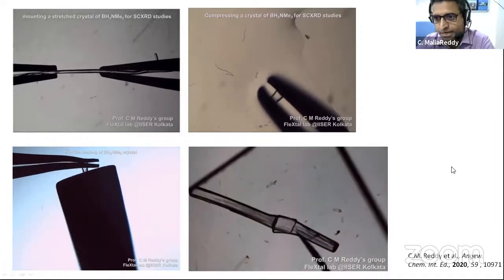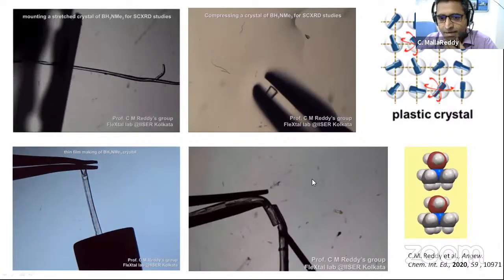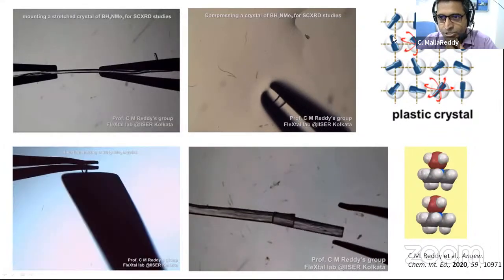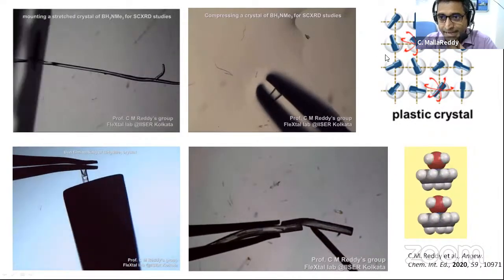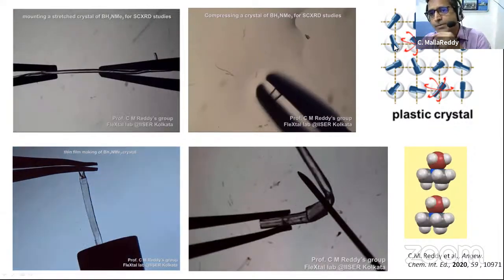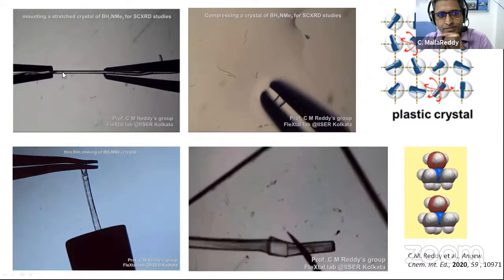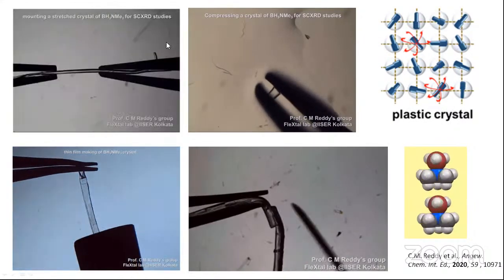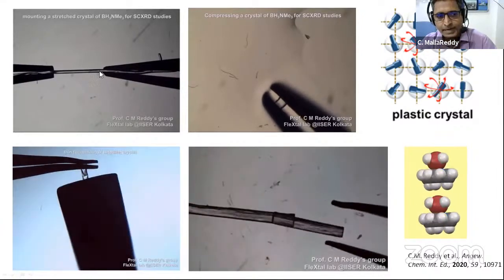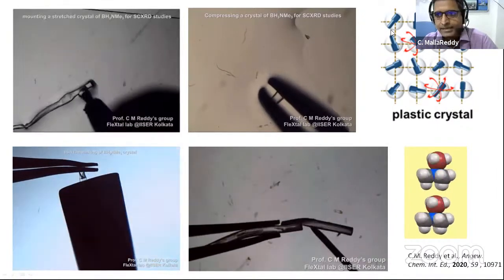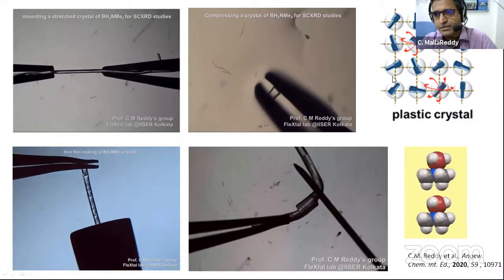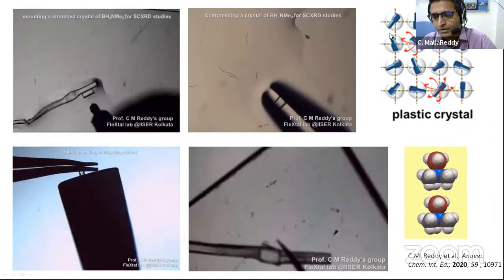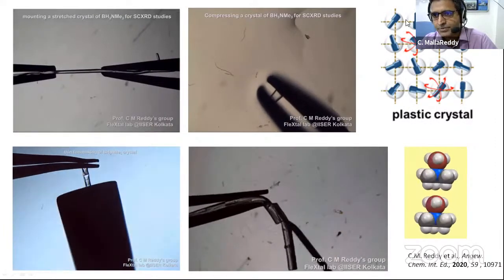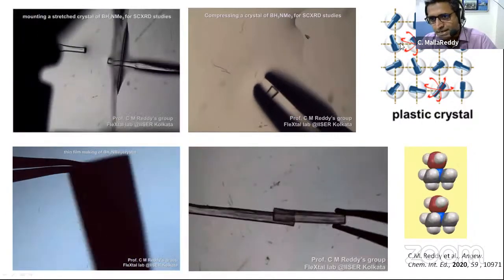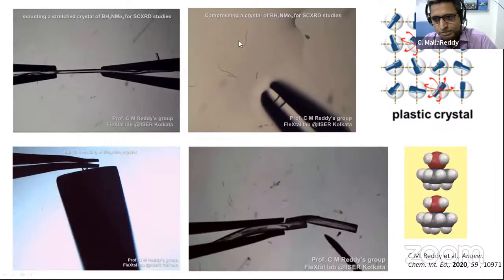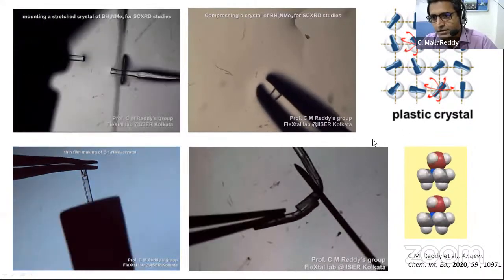So this we again tried to understand. So here what happens is the molecules have rotational freedom. Okay. So interactions between the columns, these are like columnar molecule packing. So suppose you have a crystal here, if you look at the crystal packing along this direction, molecular columns run parallel to the needle direction, and then molecules basically rotate along an axis. So that gives them more degrees of freedom, and interactions between these columns are very weak. So then you can basically slide these molecules in any direction. So that gives you all these special properties. So these are called plastic crystals or rotator phases.